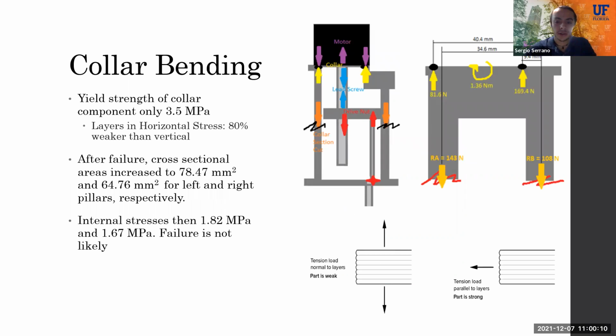As stated before, during a preliminary test of our design, one pillar of the collar broke when the plunger collided with the floor of the collar. The free body diagram shown of the collar shows that fracture could have occurred because of tensile internal stresses overcoming the material strength. It is also worth noting that the material strength for the 3D printed parts largely depends on the orientation of the plastic layers making up the component. While the yield strength of PET-G layers under vertical stress is 17.5 MPa as determined by our tensile test on the Instron, the same layers under horizontal stresses have an 80% weaker yield of about 3.5 MPa.